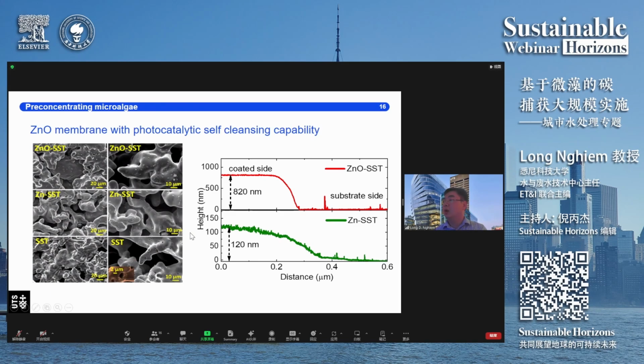As I mentioned to you before, we have two different techniques. One is to coat zinc oxide directly onto the membrane surface, and you can see the SEM image here. The substrate we use is stainless steel. It's a porous stainless steel with a very large pore size of about 10 micron, because the microalgae is large enough, and 10 micron pore size is more than enough to retain the microalgae. I should note, and I didn't show you the data, but I can provide you with information that the rejection of microalgae in our case is 99% plus. So it's very effective, even at the large pore size.